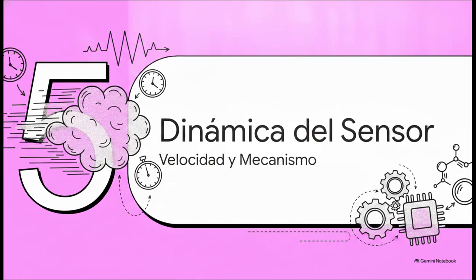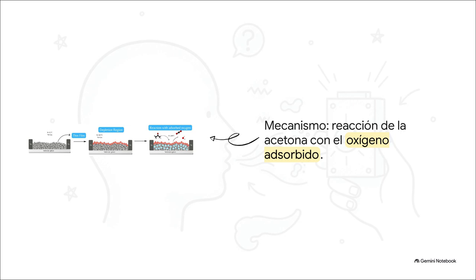Next up is Section 5, Sensor Dynamics. To understand what's happening dynamically, we have to look at the mechanism. The acetone molecules are basically reacting with oxygen ions that are already hanging out, adsorbed on the film surface. That reaction dumps electrons right back into the crystal lattice, and bam, that's your drop in resistance. In terms of speed, the response times were incredibly fast, consistently under 30 seconds across the board. The recovery times took a bit longer, hovering between 400 and 700 seconds.